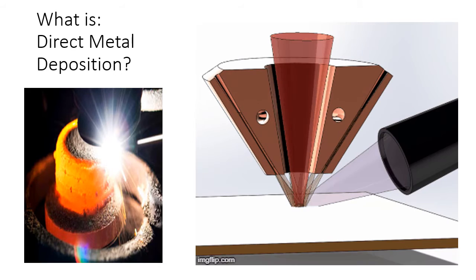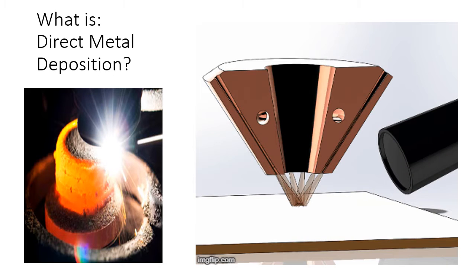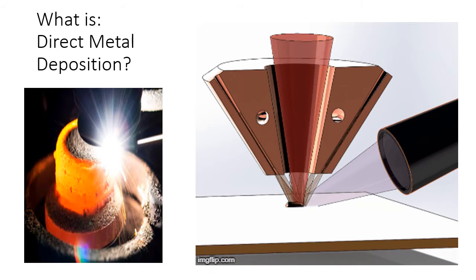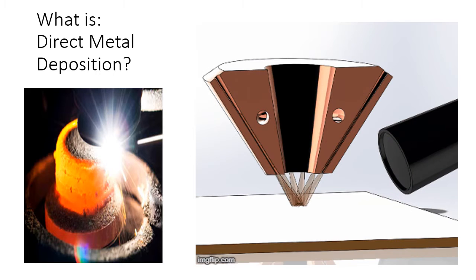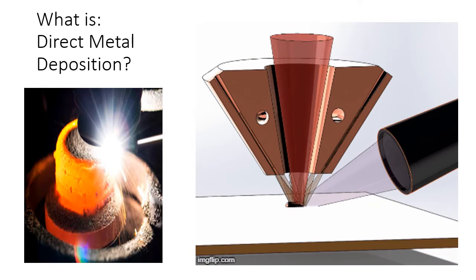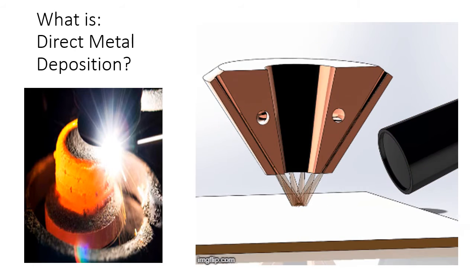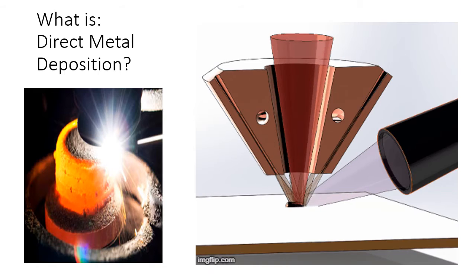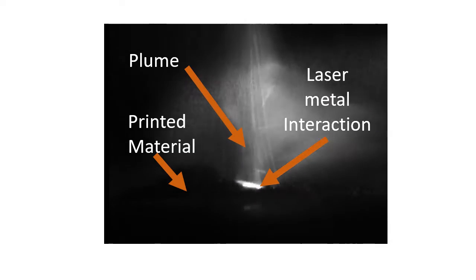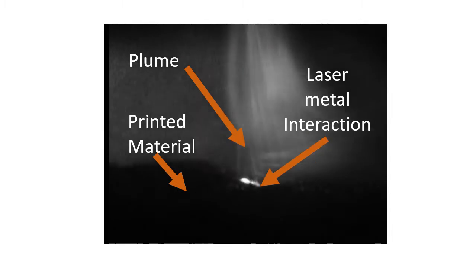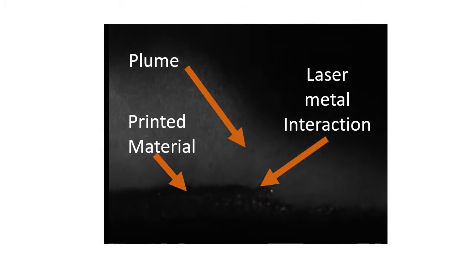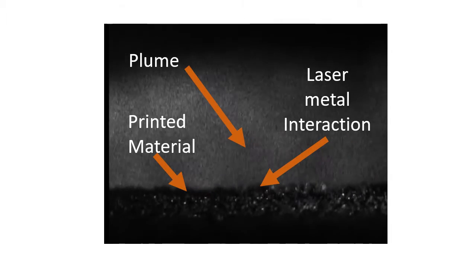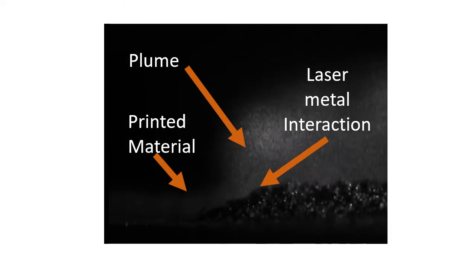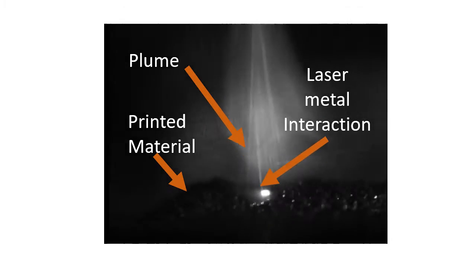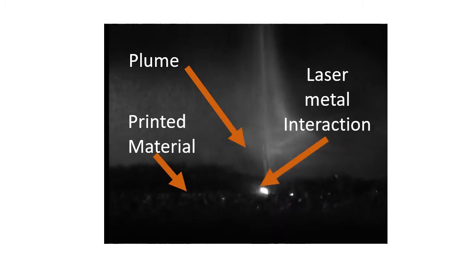With plastics, you can use a filament and a heated nozzle to deposit your 3D printed structure. But with metals, you need to use something a little bit different. With metals, we use powdered metals, and we focus a stream of powder underneath the laser, and we draw the nozzle around in the same way we would with a plastic one to make whatever shape we wanted to make. In practice, that looks something like this, where the laser goes down through the column of powder and collects and deposits a thin layer of material. Those layers can be stacked on top of each other, as is being shown right now, to make basically any shape you want to.